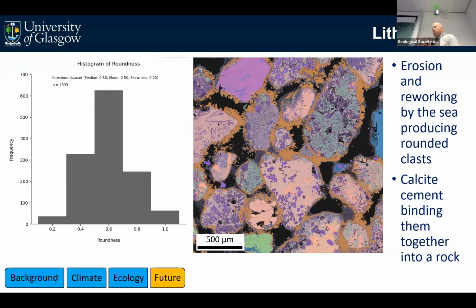And we can see that what's happened is, this is on the coast, on the Irish Sea, quite an exposed coast, lots of waves, tide energy. The waves have eroded the slag, rounded off the particles. So analysis done by my colleague Amanda, a sedimentologist, shows that the particles of slag are relatively rounded compared to what they were like when they were first deposited.